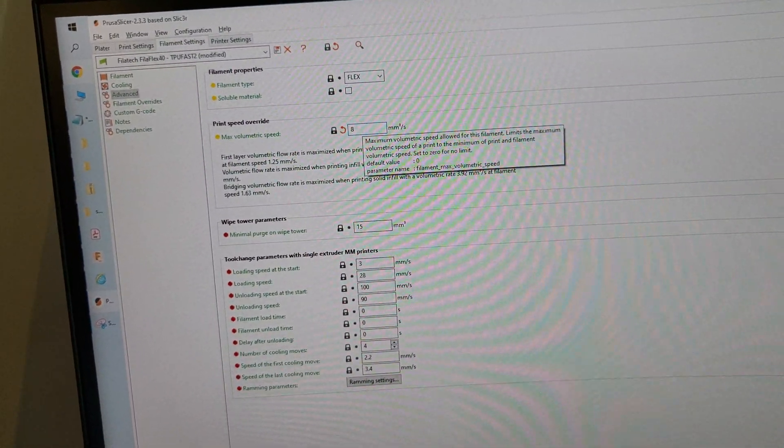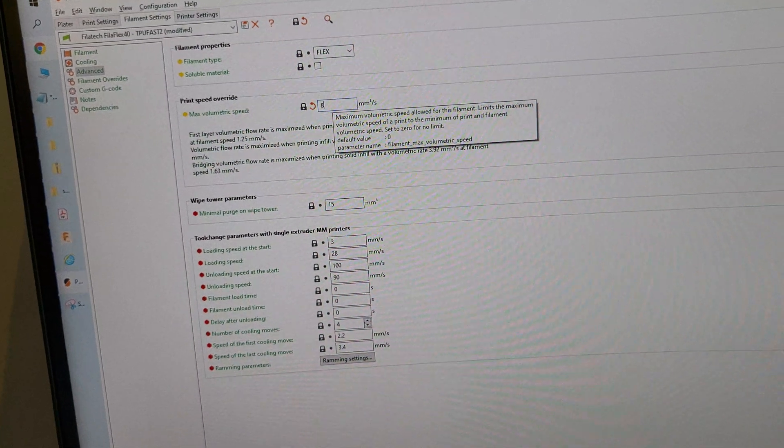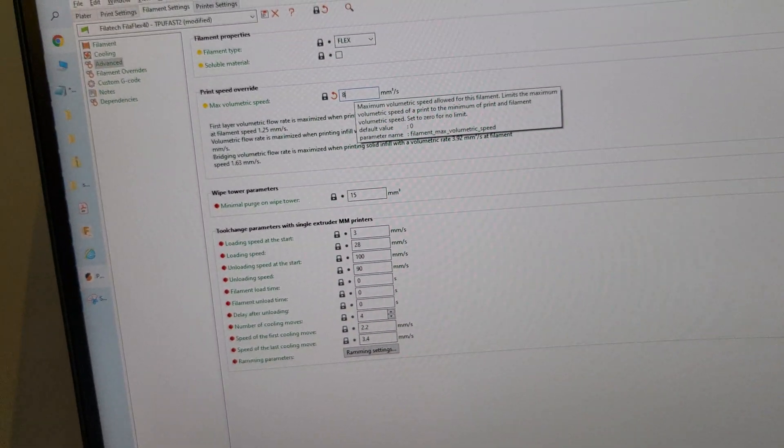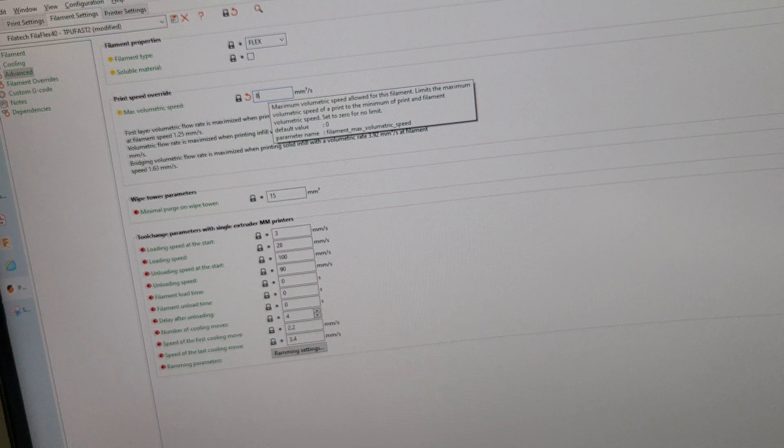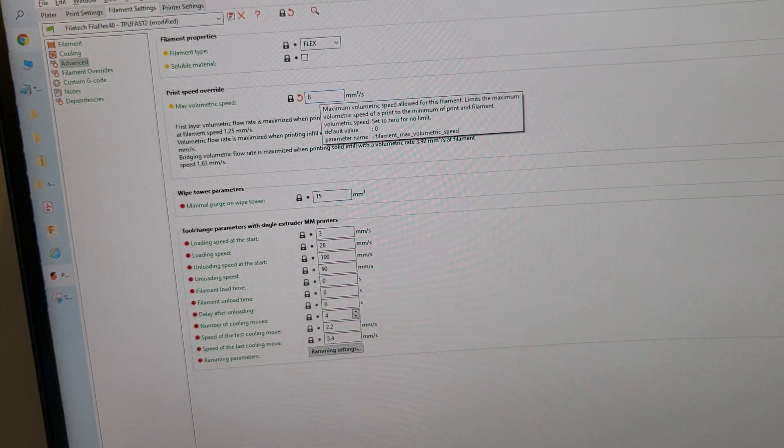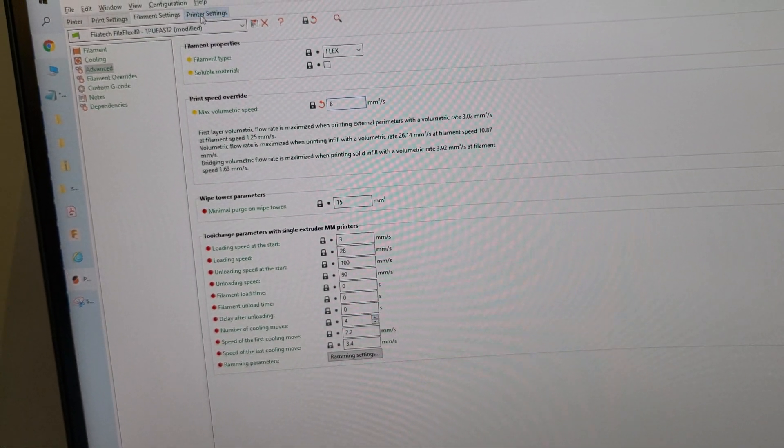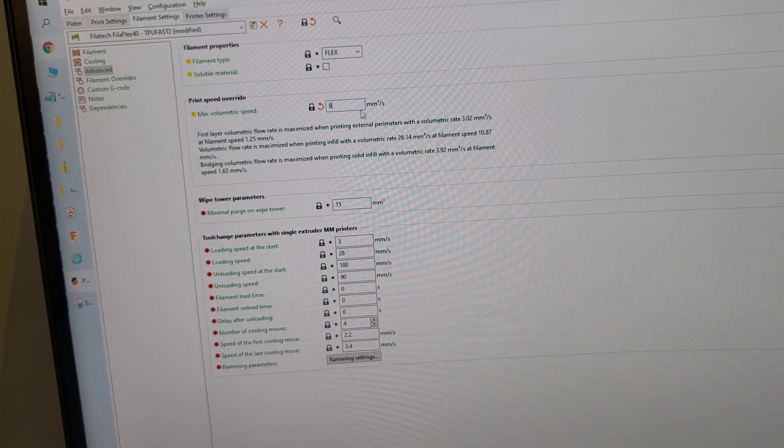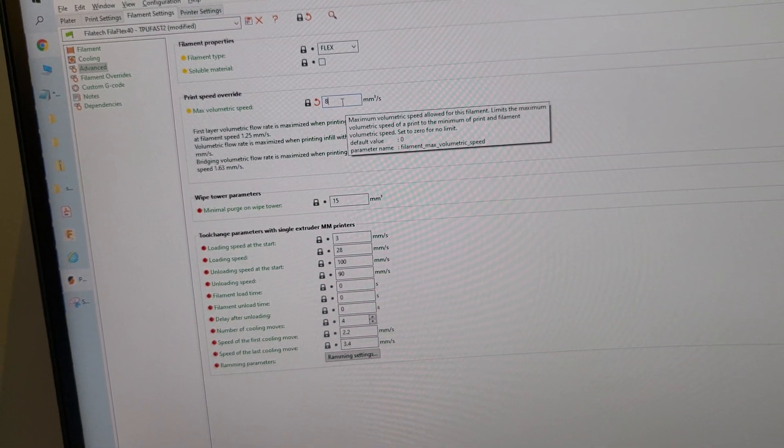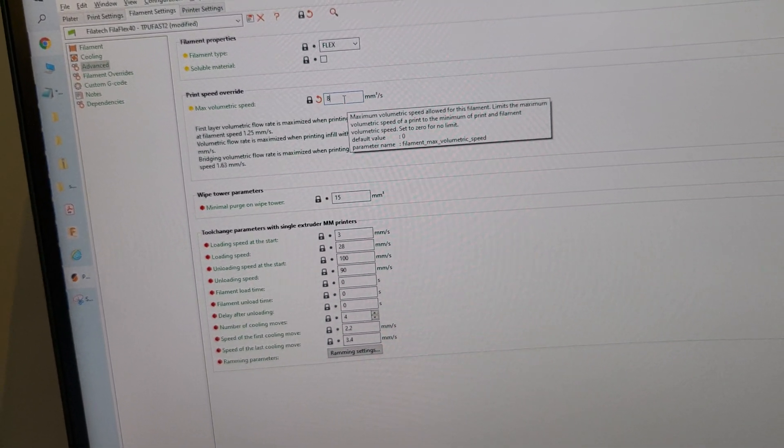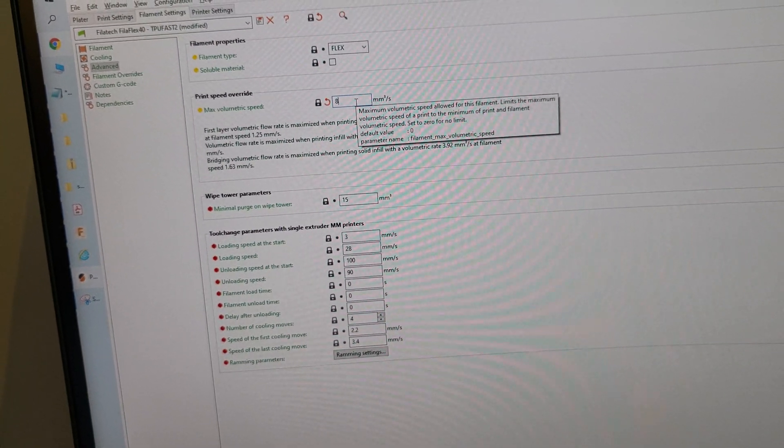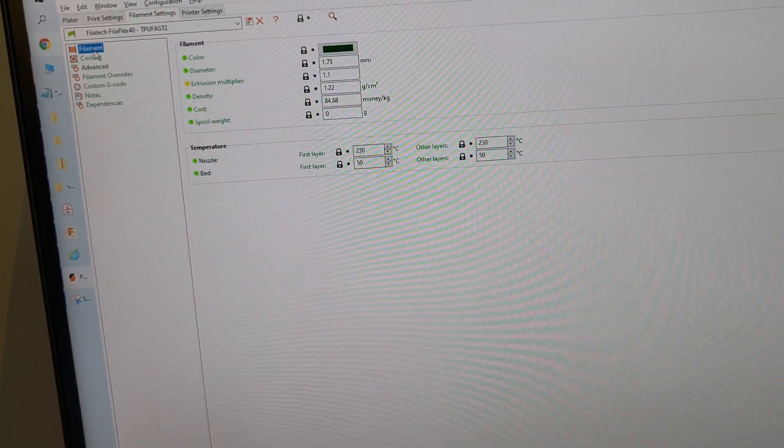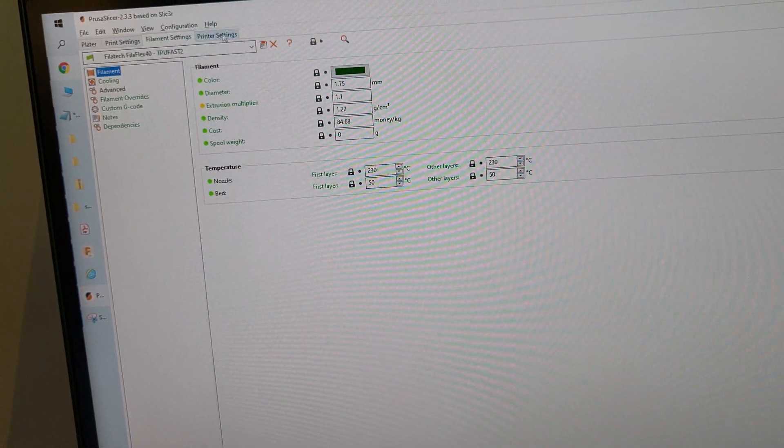Now if you want to do this, you're going to need a ball bearing spool holder because if you try this on a stock spool holder, you're going to get clogging at around even 5. But the spool holder definitely made the change and I was able to go fast. I did try 10 and you're going to get clogging, so 8 is pretty much the maximum safe number I found.